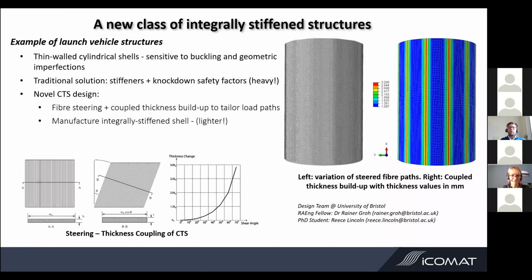What we are proposing, thanks to this shear thickness coupling that I mentioned earlier, is that if we steer the fibers on this structure, we can get a thickness increase locally as that happens, and therefore create integrally stiffened structures. So we can stiffen the structure, make it thicker locally without adding extra material, which is a bit of a new concept. And we are about to manufacture one of these cylinders for the European Space Agency, and we'll send it off to be tested.